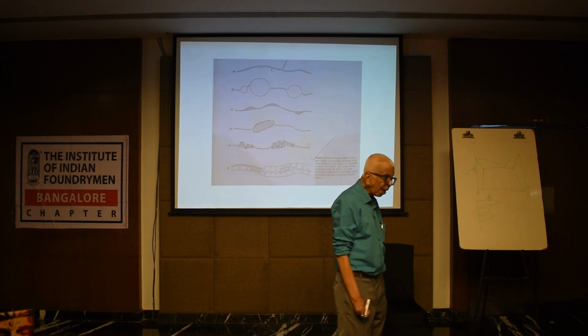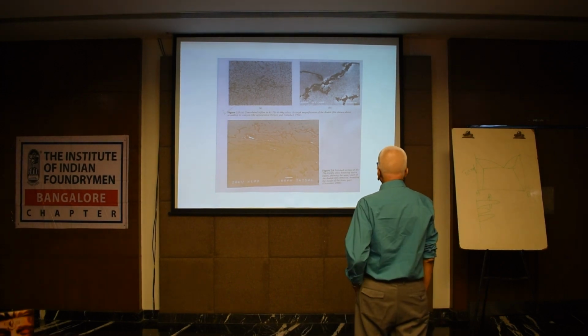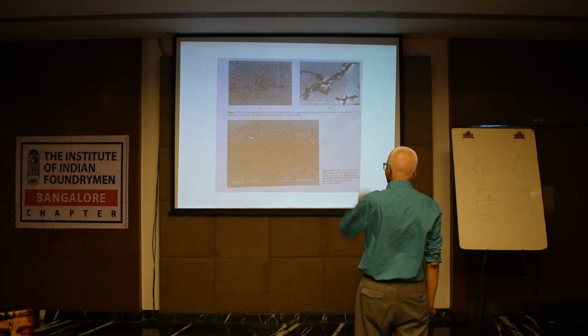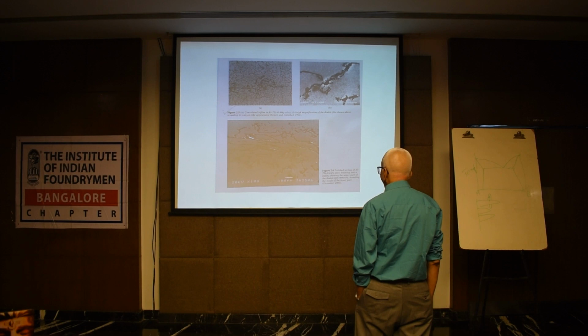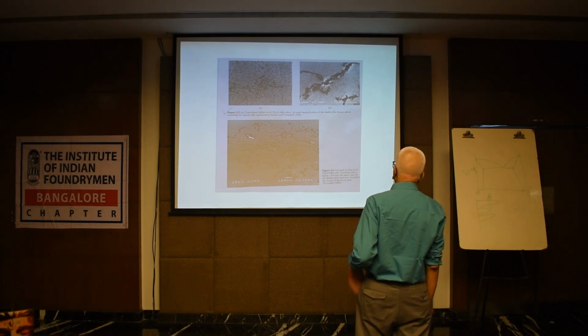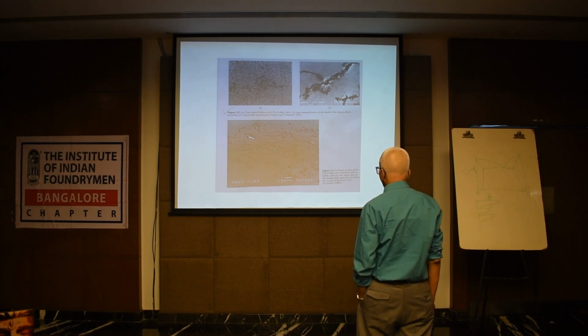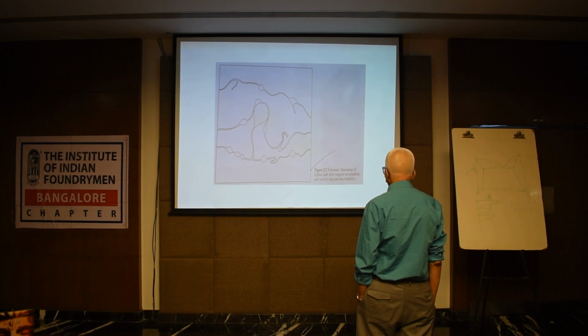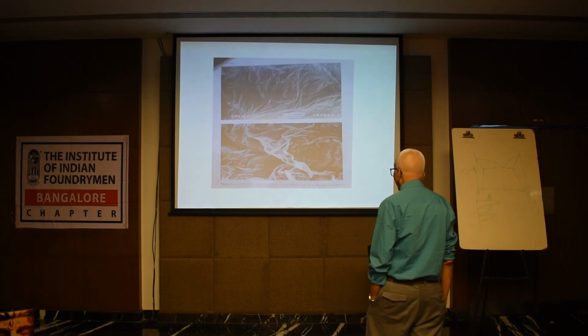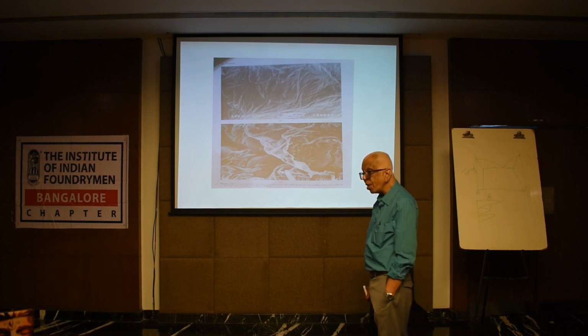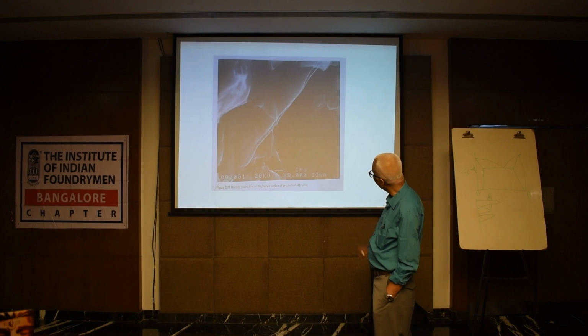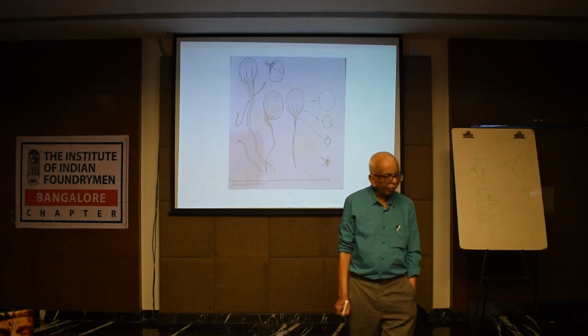He's written a book called Castings. Next slide, please. This shows the cracks in the bifilm. This aluminum 7 silicon 0.3 magnesium alloy is close to A356. The convoluted bifilm unfurls, and you can see fissures or cracks. This deteriorates all the properties of the casting. Next slide, please. This is the cracked micro bubbles. It's the same stuff. Next slide, please. There's a scanning electron micrograph of a folded bifilm, captured in the scanning electron microscope. Next slide, please. This is a bifilm, and once again you can see a crack being formed in the unfurling stage.